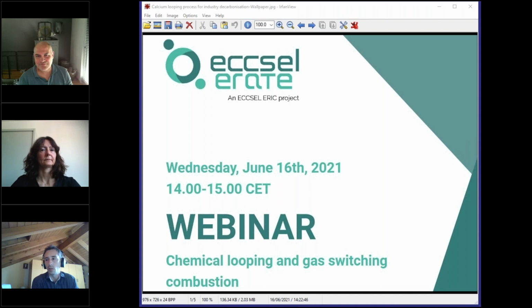In the first calculations, we were quite conservative, also in considering the low oxygen concentration in the oxyfuel oxidant of the precalciner, and that is a very important parameter, because if you increase the oxygen concentration, like we want to do in the clinker, you decrease the CO2 recycle, and you decrease the fuel consumption and the oxygen consumption itself.